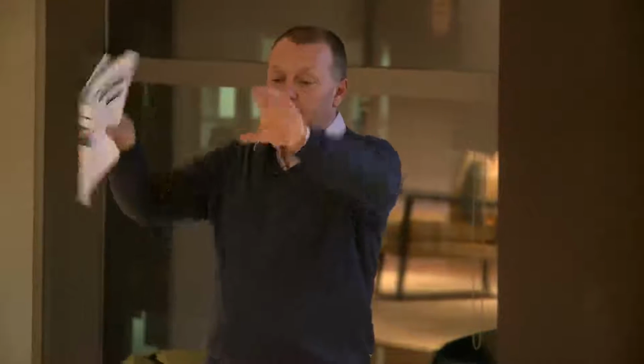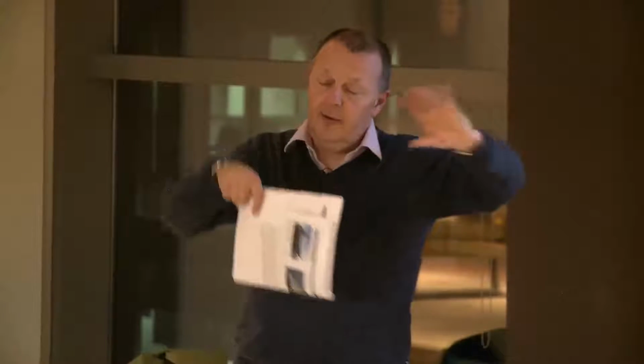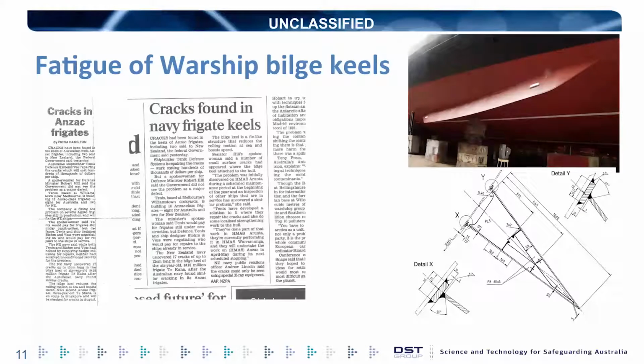So that wave loading causes the ship to hog and sag as it goes through the waves. There's lots of structural damping, and there's water damping, which means it doesn't resonate and fall into two bits and sink. But those wave loads cause global fatigue loads. The bilge keels on the Anzac class here are a plated structure. They're about 300 mil wide, about a metre long, plated structure that's welded onto the side of the Anzac ships by a couple of double plates here.